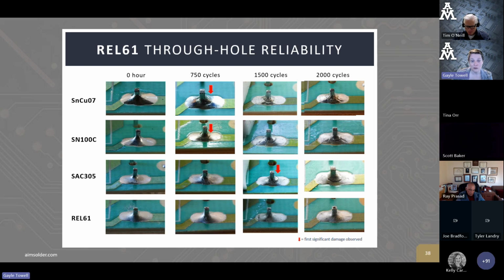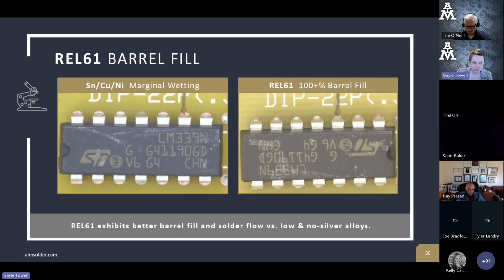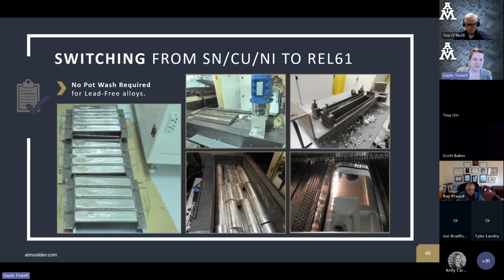It has this beautifully formed fillet, great hole fill, really good joints formed. Again, the barrel fill of REL61 tends to be better than a lot of these other low silver alloys and SAC305. We've had many, many customers that have had issues with barrel fill in their wave or their selective, switch to REL61 and it goes away. They start getting 100% barrel fill on everything. The other nice thing is if you are going from a lead-free wave to REL61, you can make that transition without needing a pot wash. So this was just an example of switching over the pot from one alloy over to REL61.